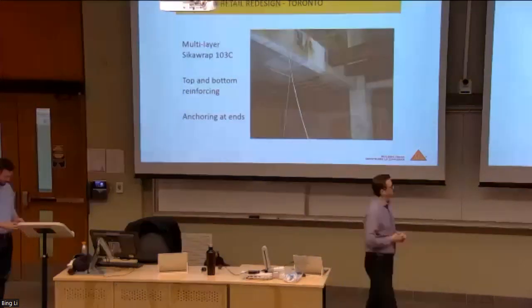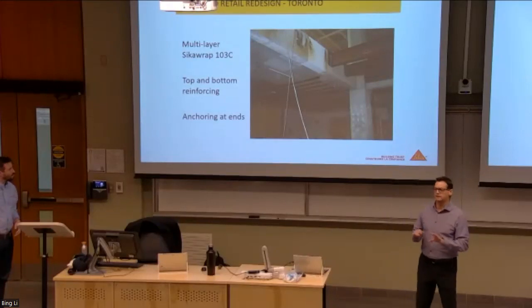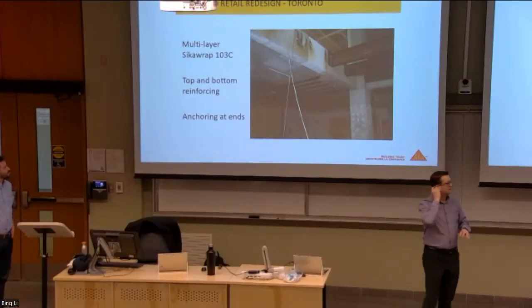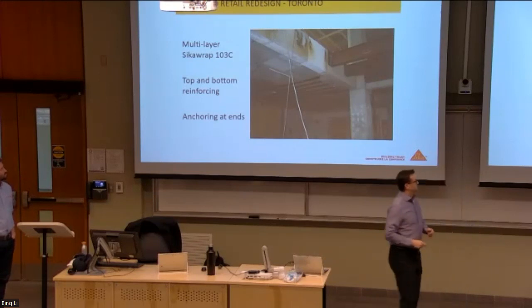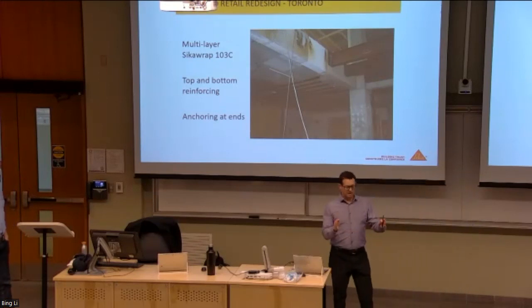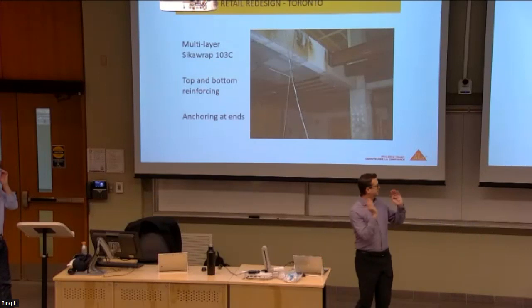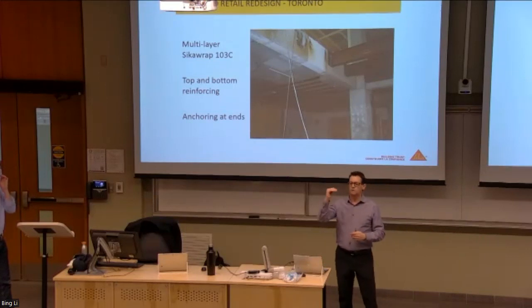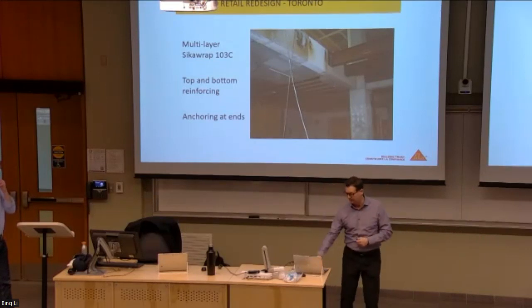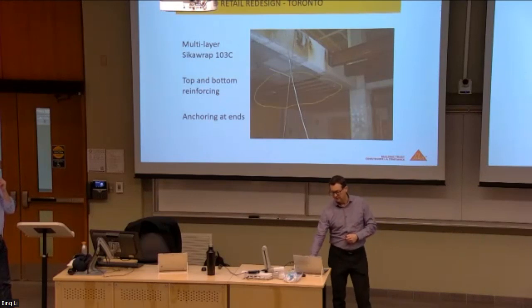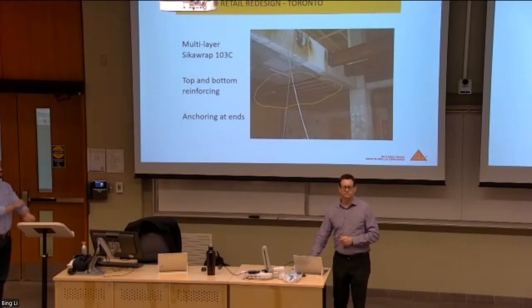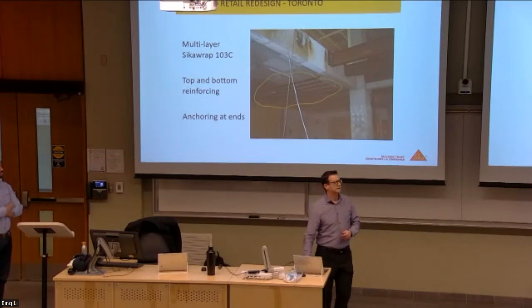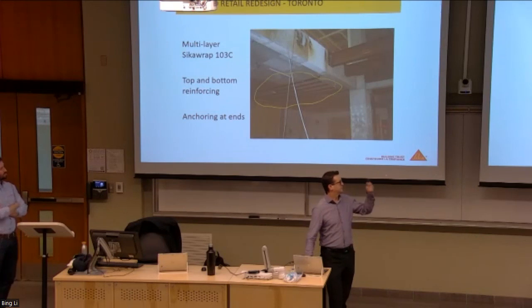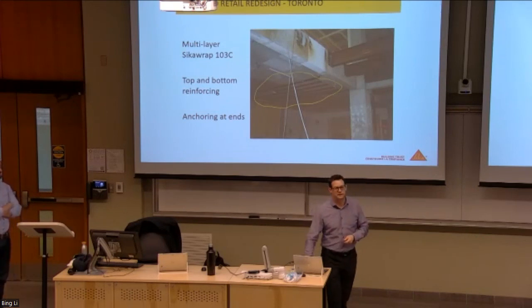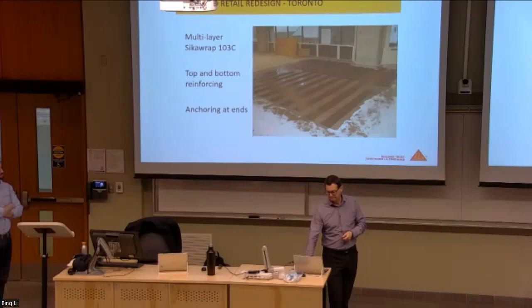So we used it. We could have used the plates here, but this is the versatility of the wraps, is we could use the wraps on the underside as well. Those wraps were a foot in width and of various lengths, and they would basically place one wrap on top of the other, and they actually wind up having five different layers of that wrap system on the underside. So it was a very heavy structural upgrade and reinforcing that was able to be accomplished with the system after taking out the dynamics of that slab.